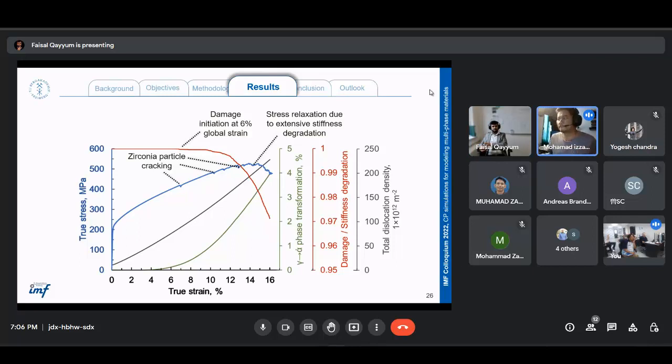Should we write the subroutine, or how is it in DAMASK? In DAMASK, do you have this kind of algorithm, or should we add our own subroutine for damage? There are already two damage models available within DAMASK. Very simple ones: ductile damage criteria based on maximum principal strain, and brittle damage criteria based on plastic strain energy. They are already there, so it just needs to be referred to with all the values given as input, and then it runs out to a subroutine which is already there, and the solution comes back.